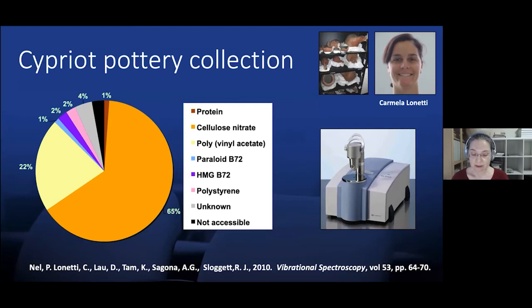There was also a small number of samples that did not dissolve in the acetone. Some were found to be water soluble and were identified to be protein-based repairs. Another insoluble sample needed to be manually removed using a scalpel blade and was compared to spectra on the commercial polymer database, and from this polystyrene was identified, which was not previously reported to be found in archaeological pottery repairs.